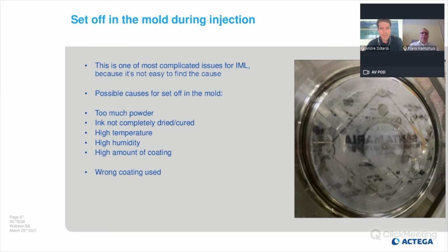Here you see a picture of build-up set-off in the mold. That means that a white, cloudy substance comes off the labels. That is the most complicated issue for IML, because it's not easy to find the cause. And there are some possibilities. Mostly it's too much powder, or the ink is not cured well enough, or you have a lot of humidity inside, maybe higher temperature. In some cases, the coating is overdosed, so there is too much coating on the sheet.